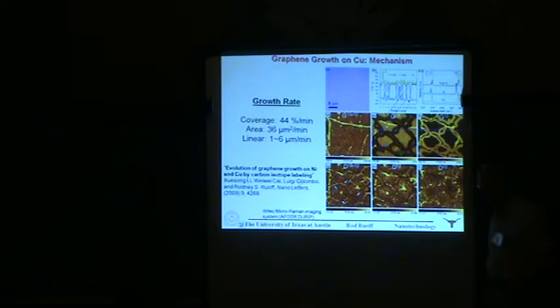In this temperature range, for graphite, it's 300 to 700 K. In graphite. What about the graphene? In graphene, it's apparently negative. I'll show some data. Is that in free space? Yeah, it's when it's suspended. But over what temperature range? The temperature range for graphene is not completely mapped out. It's over 100 degrees, I think so, yeah. So Jeanie Lau's group at UC Riverside has generated examples of suspended graphene where they get this beautiful crinkling effect, which is a consequence of it having a negative CTE. Is that two-dimensionally isotropic, or do we know? It's considered to be 2D isotropic.